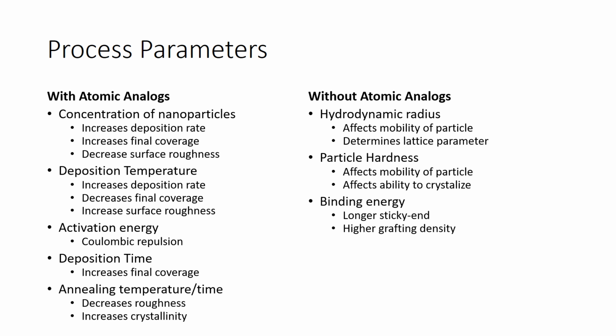We may also alter the binding energy between nanoparticles. Having longer sticky end sequences or higher grafting density will increase the bonding energy between two complementary nanoparticles.